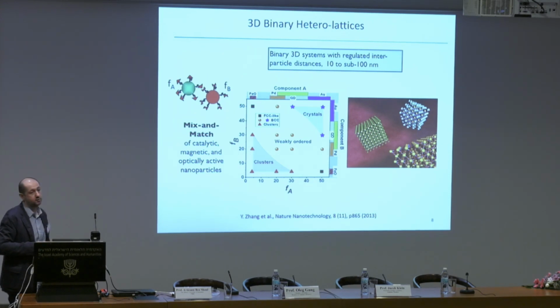From understanding when crystallization occurs and where other phases happen, we found that for particles of similar sizes, the main parameter is the number of DNA per particle, and in the regime of a larger number, 40 and so on, we obtain crystals.